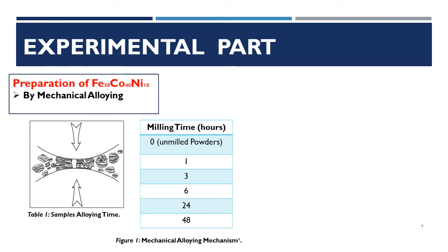For the experimental part, the iron, cobalt, and nickel element powders with high purity were milled to form an Fe50Co40Ni10 system in a Fritsch Pulverisette 7 planetary ball mill. To prevent oxidation from contaminating the powder, the vial was sealed in an argon atmosphere. The milling process, on the other hand, was designed to pause for 15 minutes every 30 minutes to avoid overheating inside the jar. The mechanical alloying was performed over several periods, up to 48 hours, in order to track the formation of the nanocrystalline structure.